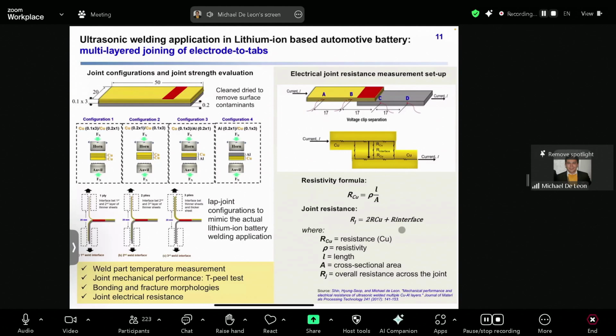For the electrical performance advantage, the UW exhibits up to 12% lower electrical resistance compared to the solder joints, which is mainly due to no filler materials involved and, of course, no flux residues. For future work recommendations, non-destructive testing is highly recommended here to detect interfacial defects.